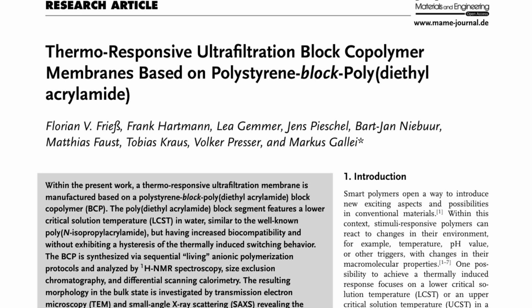The membranes are characterized using scanning electron microscopy (SEM) and water permeation measurements at room temperature and 50 degrees Celsius. The results show a significant increase in water permeance, up to 23-fold, when the temperature crosses the LCST of the PDEAAm block segment in water.